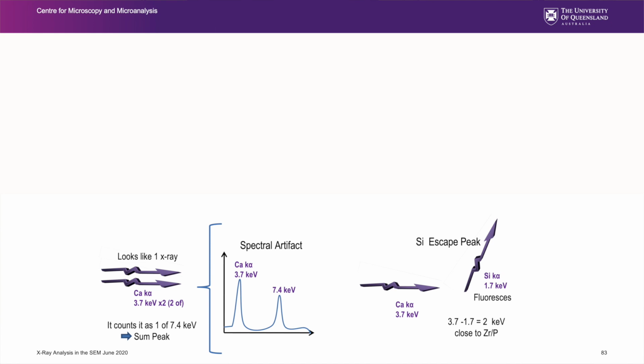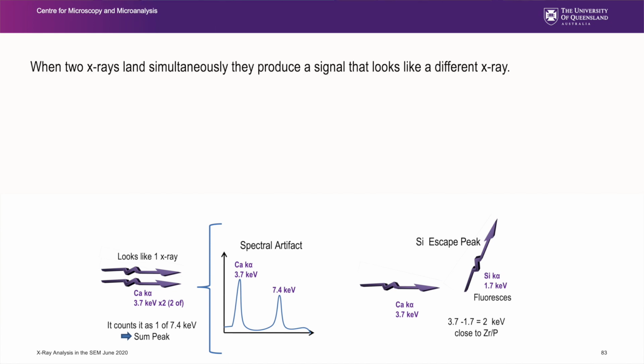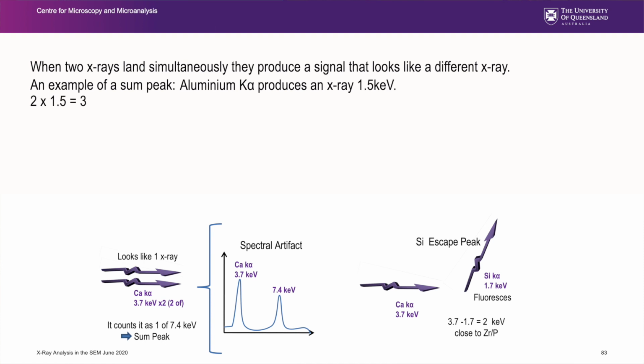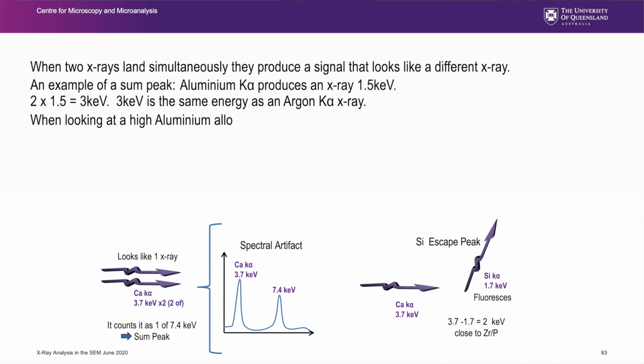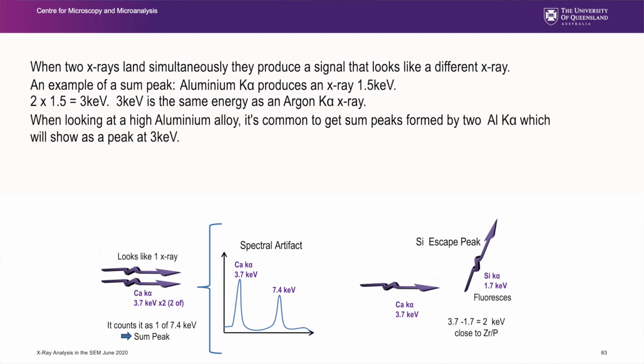You do see that in detectors where 2 X-rays land simultaneously, they produce another X-ray. Another good example of a sum peak is aluminium. Aluminium produces an X-ray, aluminium K alpha, 1.5 keV. 2 times 1.5 is 3 keV. 3 keV is the same energy as an argon K alpha X-ray. When you're looking at a high aluminium alloy, it's natural to get some peaks formed by 2 aluminium K alphas, which will be a peak at 3. Argon, which is a noble gas, you do not have argon in solid solution in your aluminium alloy. That is a sum peak.